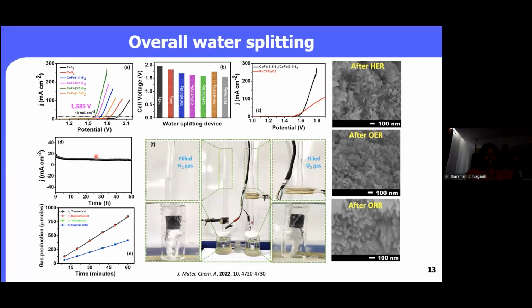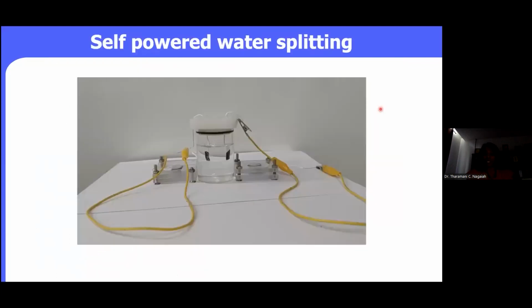And again, the stability of this device has been monitored at various current densities for a longer duration, and it is quite stable. And we have quantified the amount of hydrogen in this case by water displacement method. And also to understand the stability of the catalyst, we have performed the post analysis by SEM and XPS as well. And we did not see any changes in the morphology and also the elemental distribution in this catalyst.